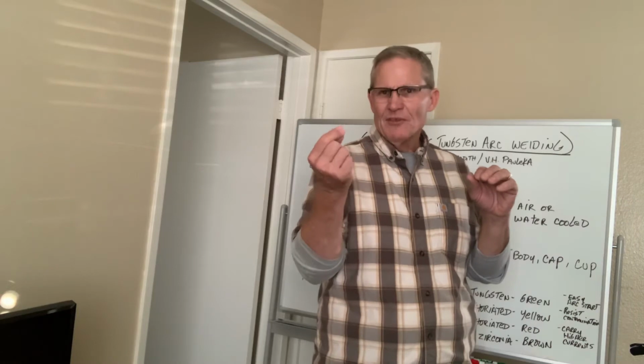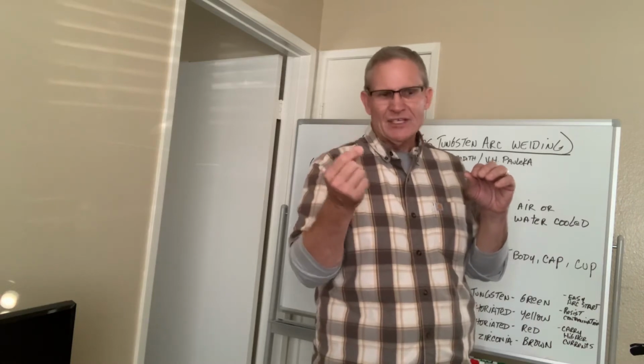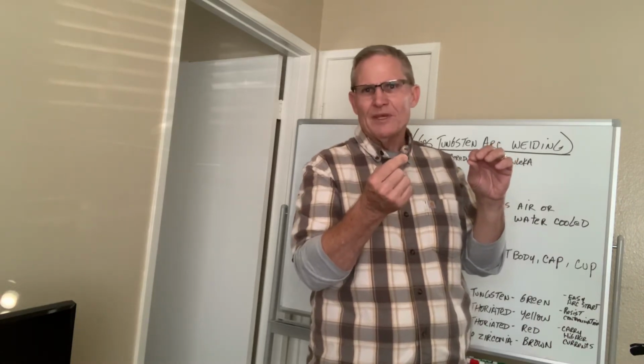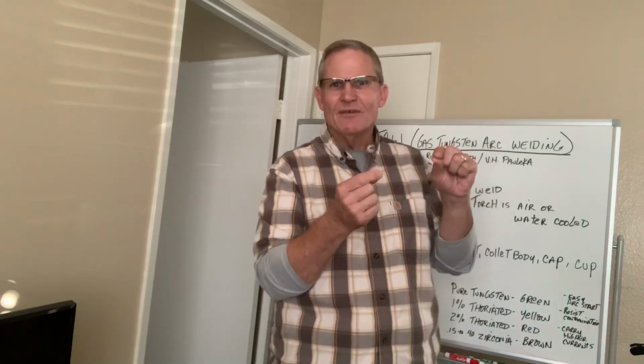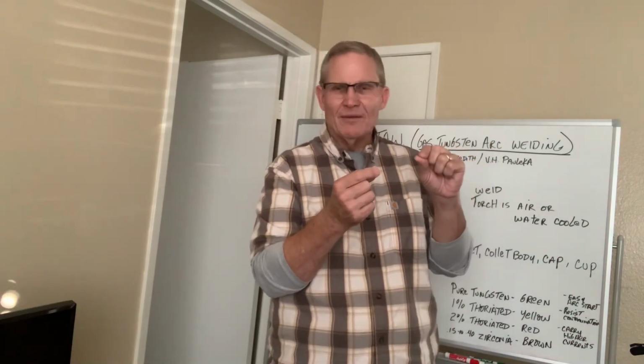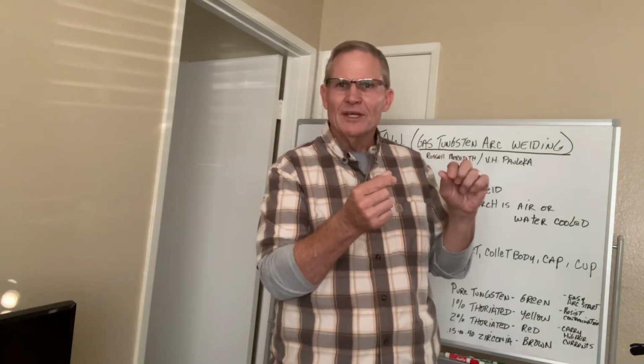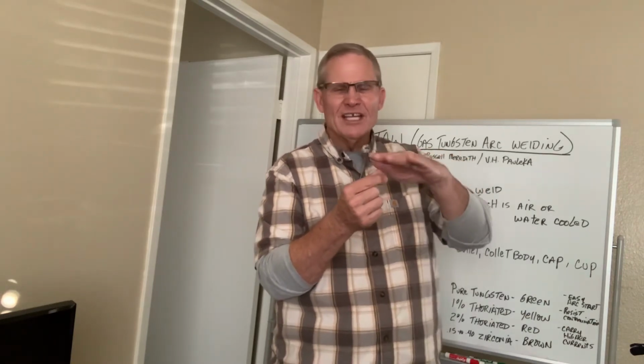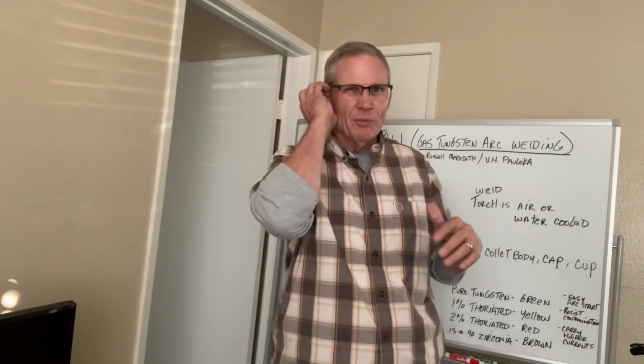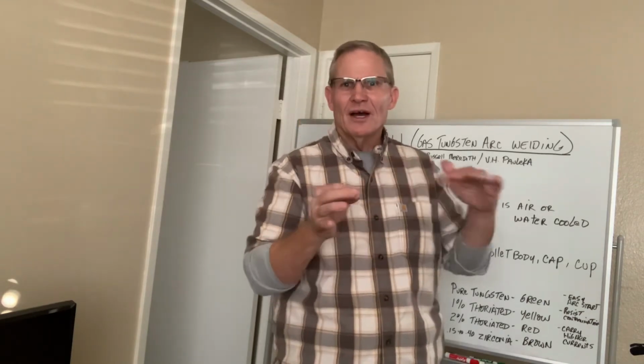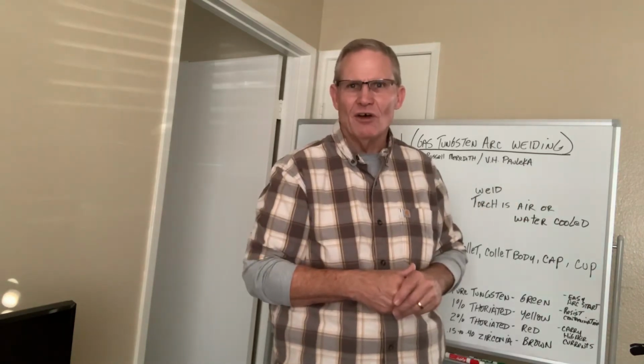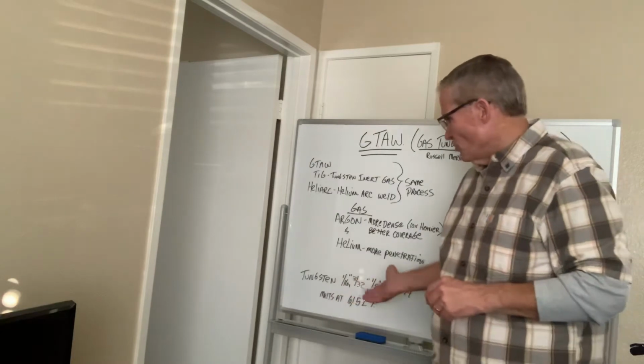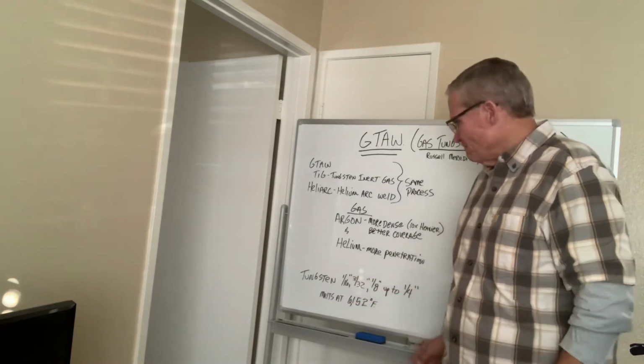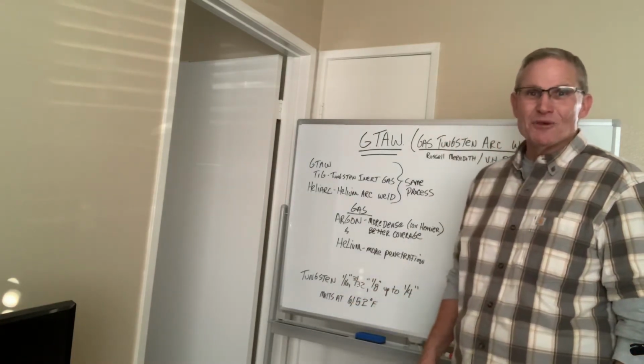So if I take that 3,000 degree match and I put it right on the corner of that piece of aluminum, even though that piece of aluminum foil, if you will, is less than a 16th inch thick, it won't melt. The reason it won't melt is because the heat transfers through the aluminum quickly enough that it just transfers it and doesn't melt itself. Same thing applies here with the tungsten. Keep in mind that tungsten is non-consumable.